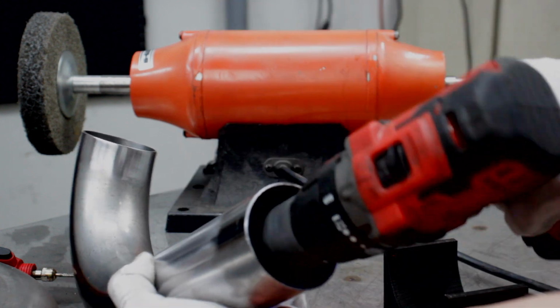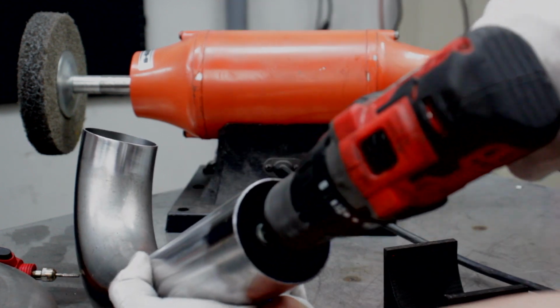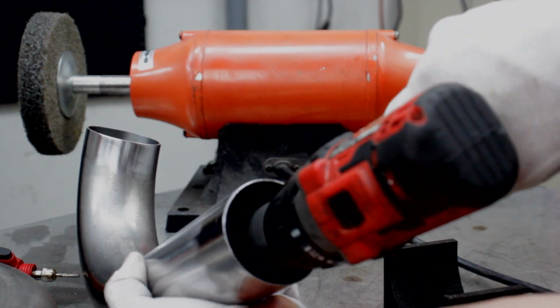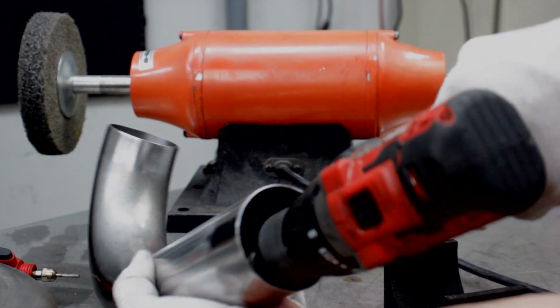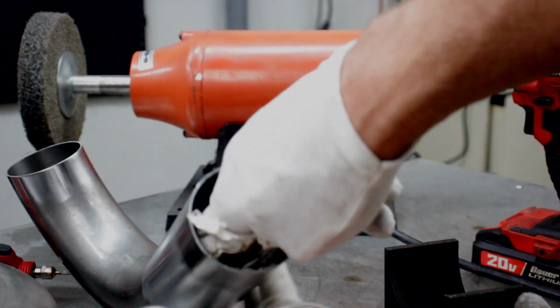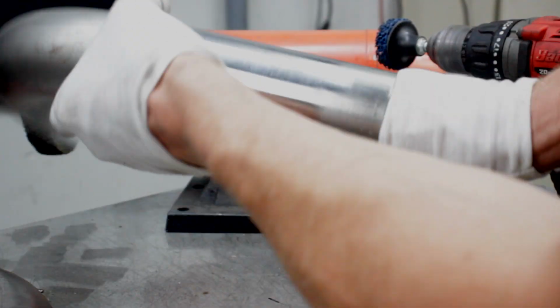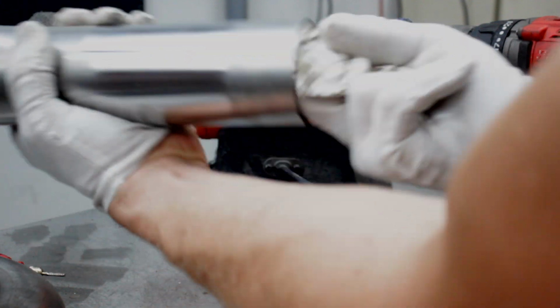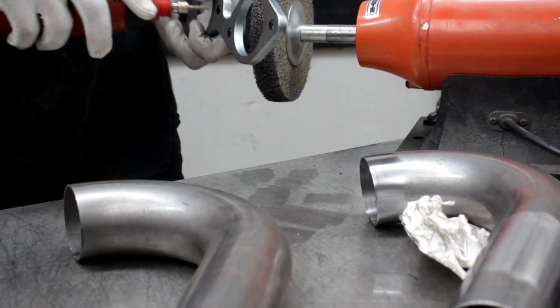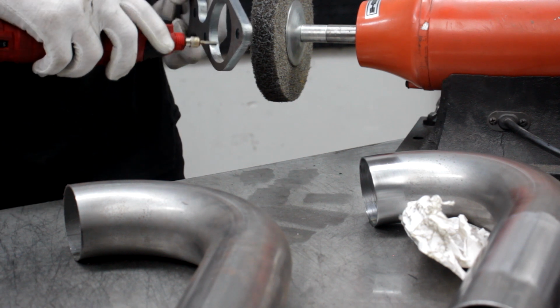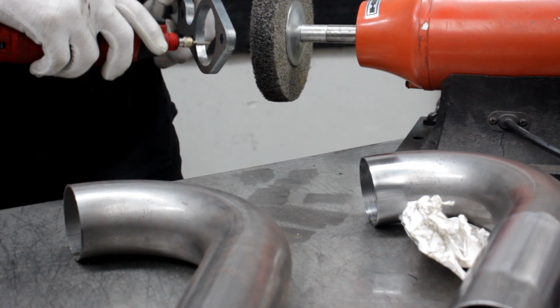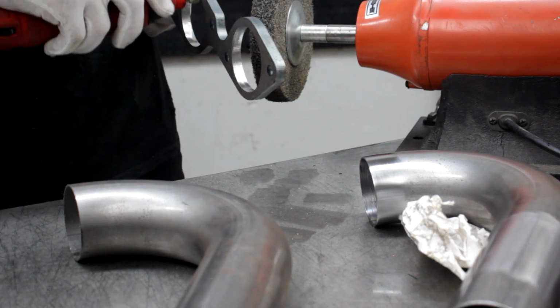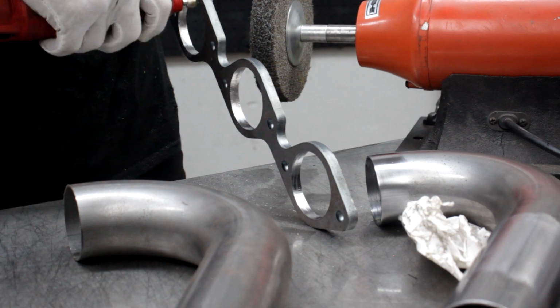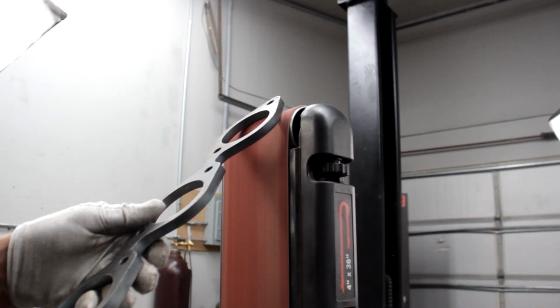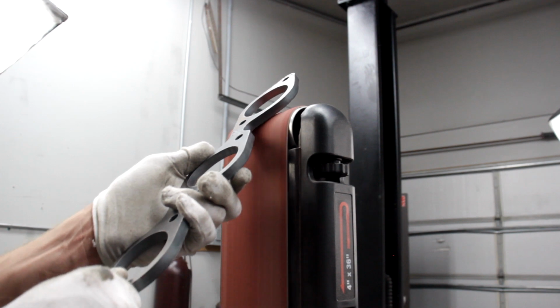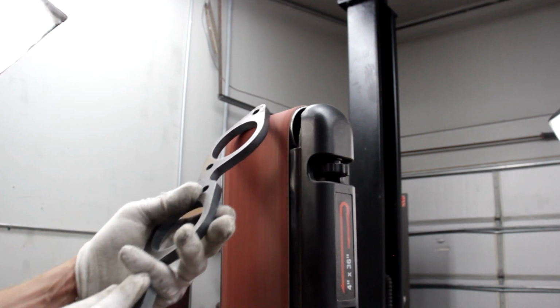Now, we really shouldn't even be penetrating into the tube too much. On a fillet weld, what will oftentimes happen is you'll suck back on the inside of the tube. And that is something we really, really, really want to make sure we avoid. We don't want any suck back on the inside of our tube. That's a really common cause for cracking on pieces like these. So the way to prevent that is, one, we don't want to run too hot on the fillet welds on the bracket, in between the bracket and the tubes. So we want to have the correct amperage input, and you want to make sure that you're introducing enough filler rod into your weld. That's a huge part of reducing your chances of having suck back.